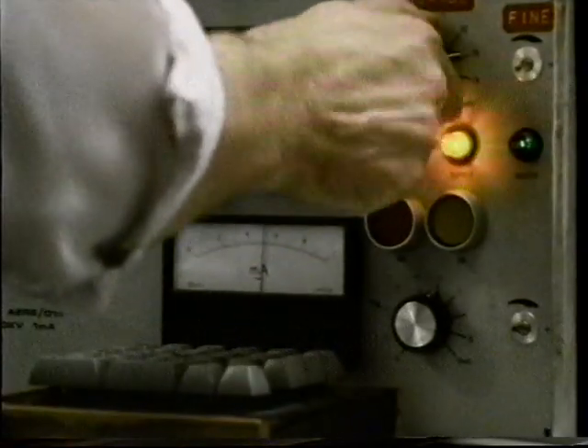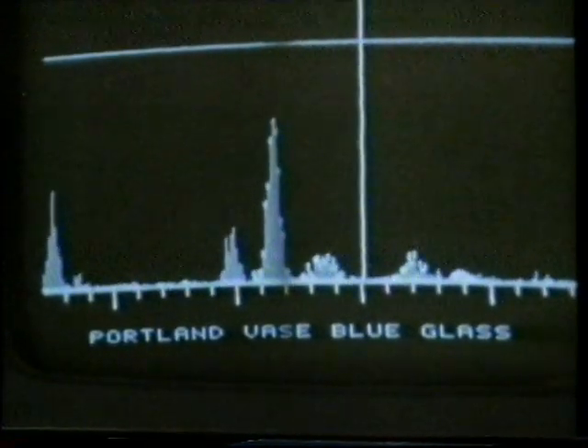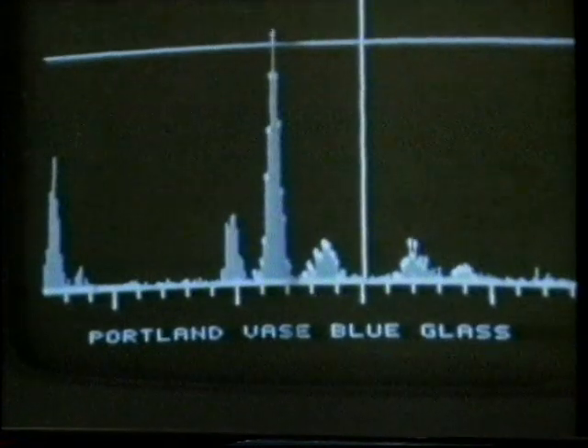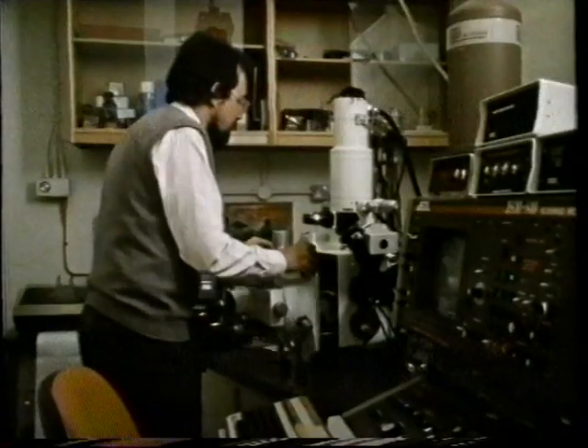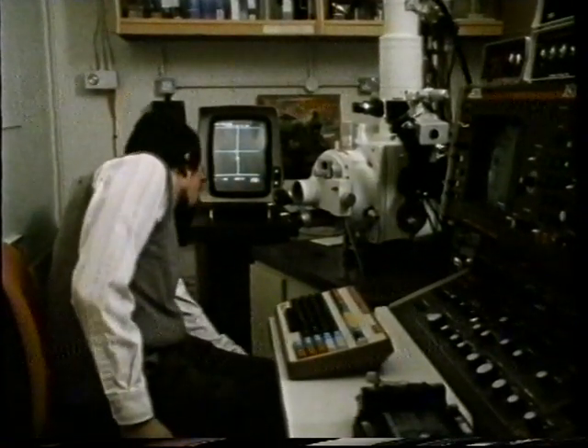As well as having the vase in 187 pieces, it can be analysed without having to break it. The research laboratory's X-ray can reveal the cobalt colorant of the blue glass in its exact quantities. Even smaller fragments, under the scanning electron microscope, give greater insight into Roman technology. Glass-blowing Roman imitation. Here, magnified over 1,000 times from a millimeter of the vase, is the interface between the blue and the white glass. The bubble is air trapped in the glass at the time of making.